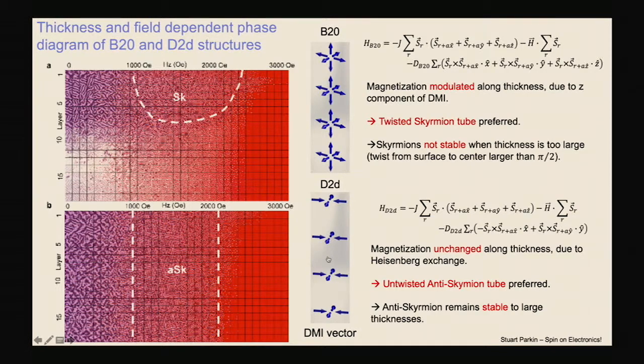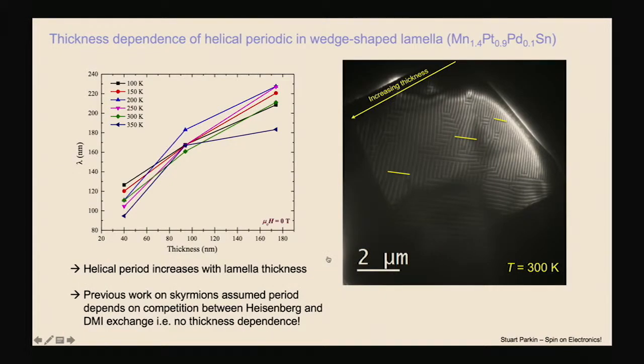Very simple to understand. In these D2d systems which stabilize antiskyrmions, there is no variation of the Dzyaloshinskii-Moriya vector component in the tetragonal direction. So that means independent of thickness, there's no reason why the antiskyrmion structure should have any twisted structure in that third direction. Whereas in a cubic system, the B20 system, in all directions you should modulate the magnetization. So you should expect that the skyrmion tubes disappear as you increase thickness. This is what we find. So we think this is a very fundamental point.